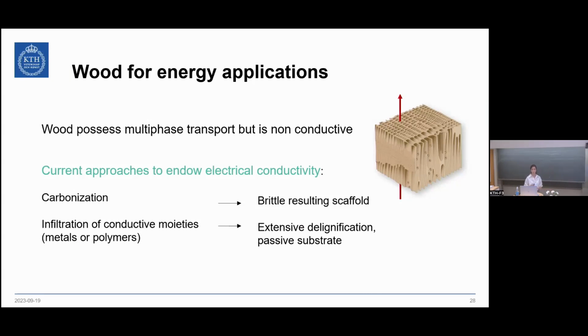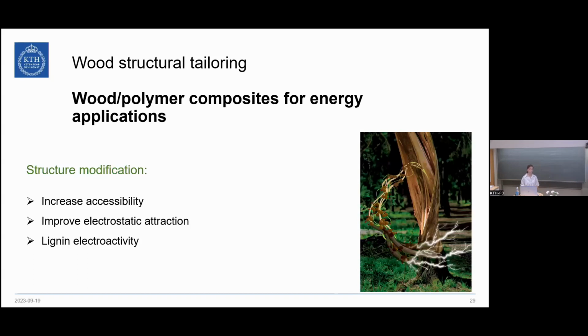electrochemical properties. So what we focused on in our case was wood polymer composite, but what we wanted to do was, of course, increase accessibility so that the material could flow better inside the wood structure. But at the same time, we wanted to improve the electrostatic interaction, attraction actually, between the wood and the polymer, because we wanted wood not to be just a passive substrate. And in this regard, we also wanted to preserve the lignin.